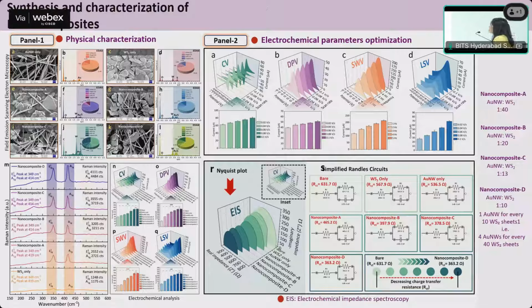So, what he has done, he has mixed the two components as a nano hybrid. So different molar ratios were prepared to understand which molar ratio is working best for the sensor application. And the same EDAX analysis shows the elemental composition where you cannot really say much difference in the elements because elements will be same. Then the Raman spectra was carried out to understand that the WS2 nanosheets are maintaining its structural integrity because it's conductive in nature. So you can see this is only WS2, and when we are increasing the molar ratio, you can see at nanocomposite D, there is an increase in the Raman intensity at specific peaks, which says that the material is maintaining its structural integrity and can be used further for sensing applications.